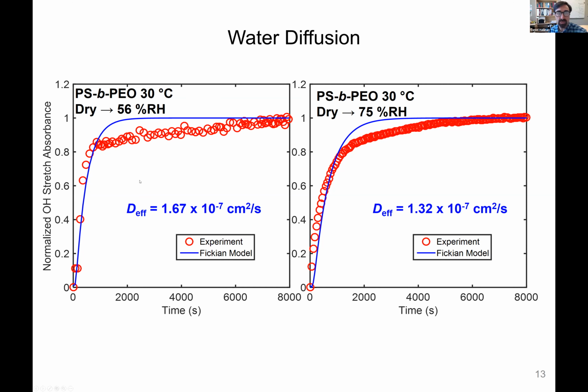So the only adjustable parameter in the model is the diffusion coefficient, and that was adjusted to minimize the error between the model and the experiment. And you can see that the model doesn't actually fit the experiment very well in either of these experiments.